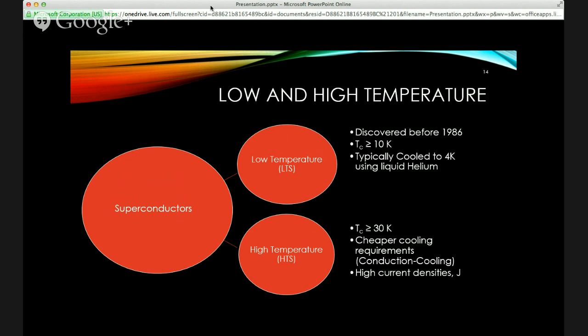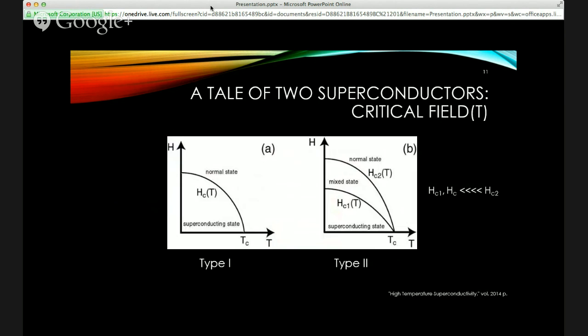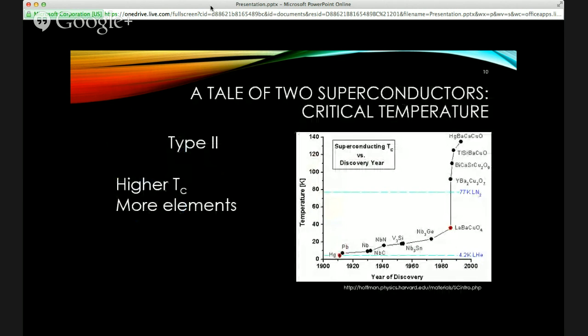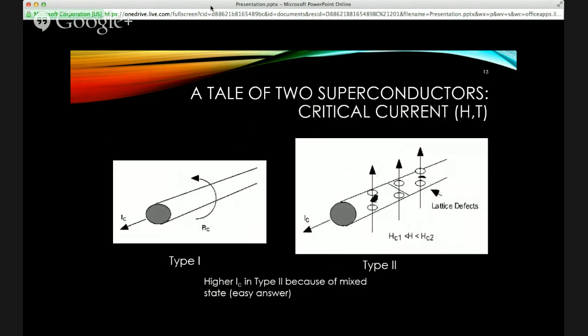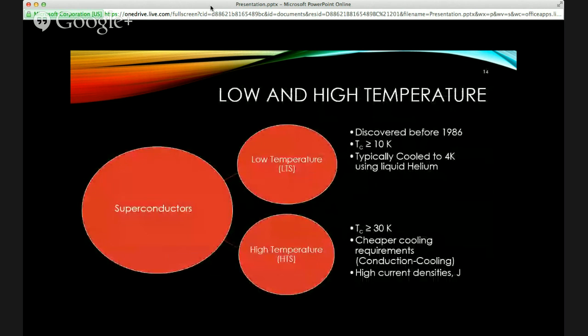This refers to that critical temperature. You have low temperature and high temperature. The low temperature, or LTS, superconductors were discovered before 1986. They have a critical temperature less than or equal to 10 K, and they are cooled using liquid helium. So if I go back here, you can see where the transition between low temperature and high temperature sits. Around the niobium line, those are what we consider low temperature. And then high temperature superconductors, or HTS, have a TC greater than or equal to 30 K.